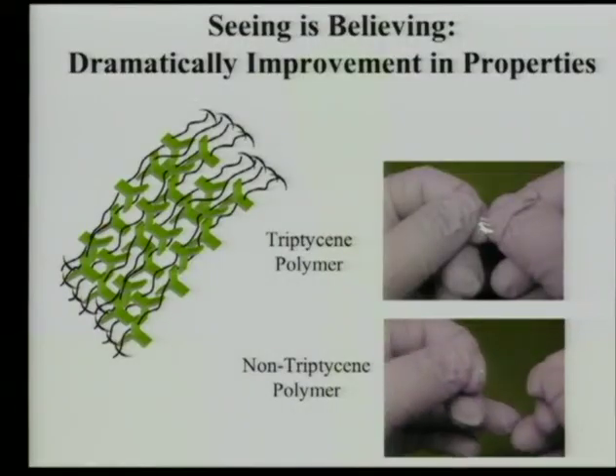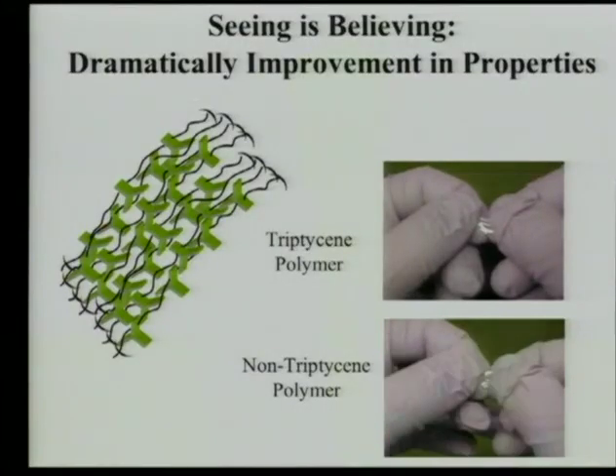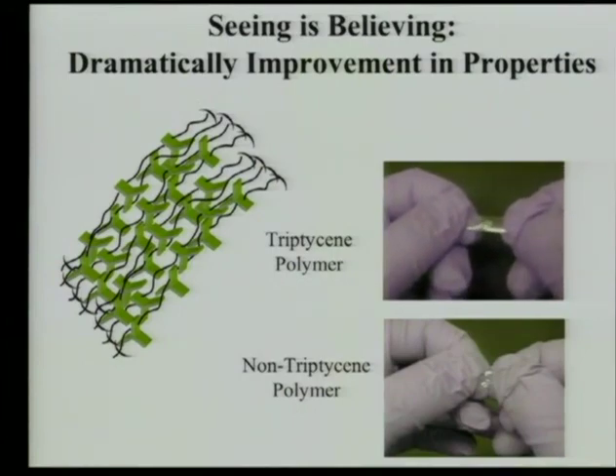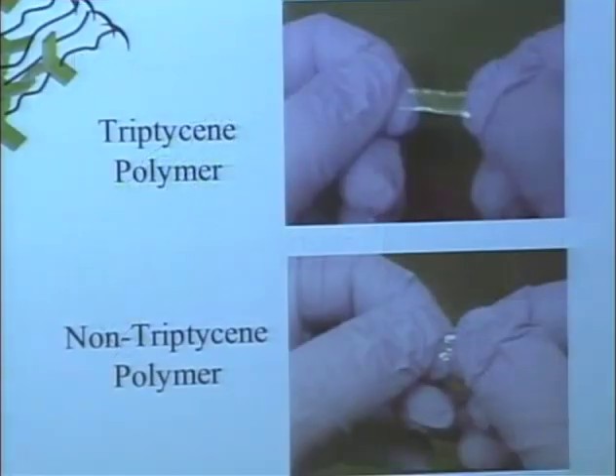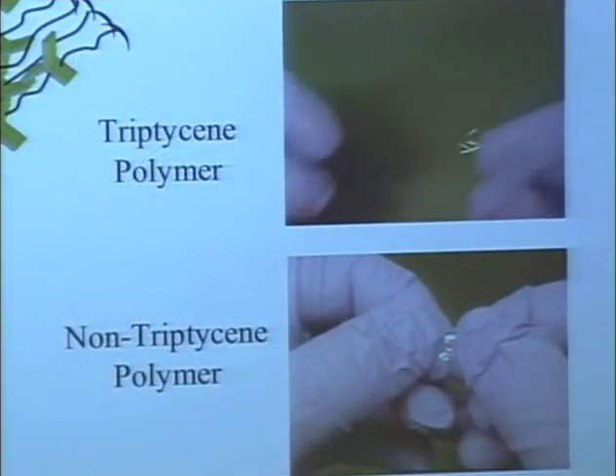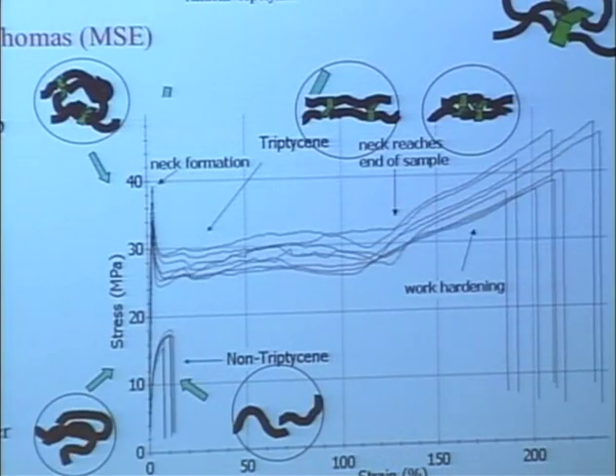Well, we found that it's a very robust design principle, and it seems to work pretty well. So this is a polyester we made that has none of this triptycene in it, the exact same molecular weight, processed the same way, same thickness, and this is with the triptycene, a much stronger material. That's not exactly an analytical study, but the story of this is I went in the lab and I saw this and I said, this is great, we've got to get a video.